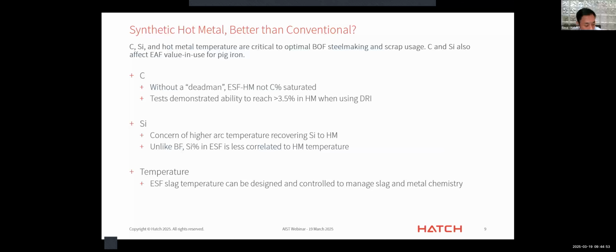So we'll go into a little bit into each of these elements. Again, I won't go into the exact dynamics of it, but more about the practical experience we've had working with these furnaces over the decades. I think the number one question, of course, is carbon. Without a dead man, ESF hot metal is not expected to be fully saturated. But our tests have demonstrated that when we use typical DRI, commercial grade DR, achieving well above 3.5% carbon hot metal is doable. And we've been testing a lot of proprietary technologies and furnace design tools to enhance that, and some have proven quite effective. So 3.5% or more is certainly doable.